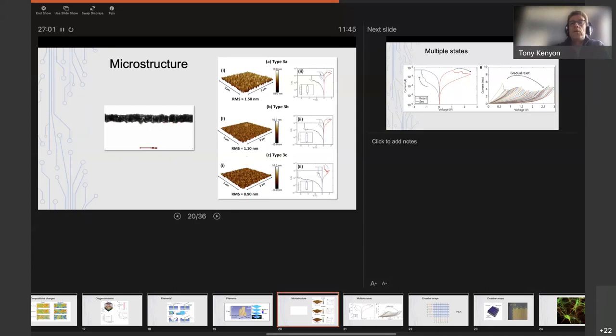So what we did was we took three different samples where we measured the roughness of this bottom electrode with this atomic force microscope. Then we deposited an oxide on top and a top electrode, and we measured the electrical characteristics. For the smoothest sample, this is an RMS roughness, a measure of the mean roughness, if you like, across, in this case, a 2 micron by 2 micron area. The smoothest one has an RMS roughness of a bit less than a nanometer. The roughest one, about 1.5 nanometers. So here are the AFM images. Here are the corresponding IV characteristics, and we see one really important thing.